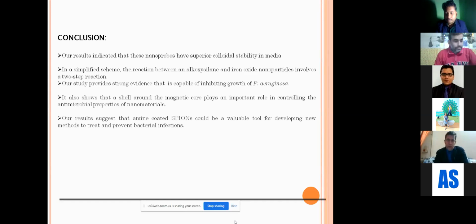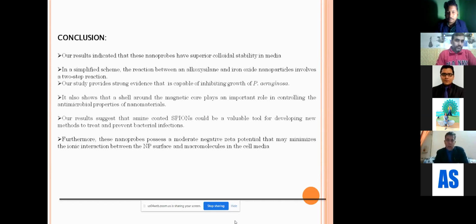So this is very important, and we could conclude that these nano probes possess a moderate charge in the form of zeta potential, where we studied that either binding with the surface of carboxylic group or with the amine group, any surface charge is still holding on to the surface, and we could see that there was a much charge present on the surface even after binding with these compounds.